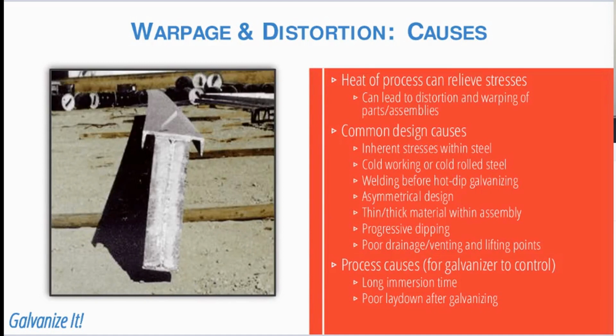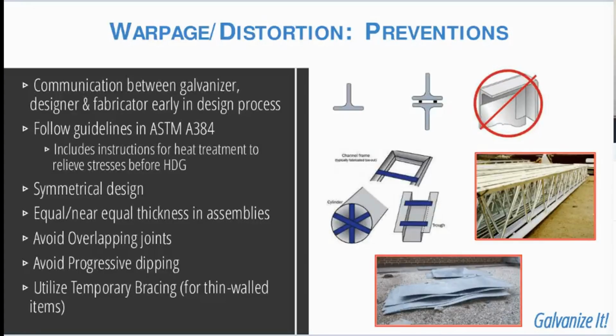The use of progressive dipping is considered an influencing factor simply because you're heating the part unevenly multiple times. And then also poor drainage and poor lifting or lifting points. These can allow zinc to clog within the part and provide excess weight that may introduce a bow into the material. These practices, where possible, should be minimized, but there are mitigations that can be used as well.